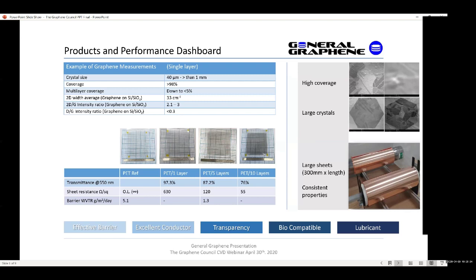Finally, notice that a single layer of graphene improves the barrier properties of some substrates by a factor of 4, and multi-layer graphene, when paired with certain polymers, is both ultra-thin and virtually impermeable. So summarizing the benefits to industry, single and multi-layer graphene is an effective, very thin barrier material that is transparent and conducting. Its biocompatibility has been well established, and graphene can also add strength to composites and act as a surface lubricant.